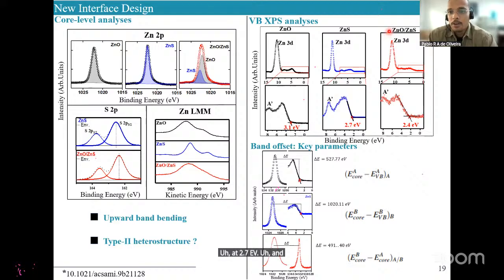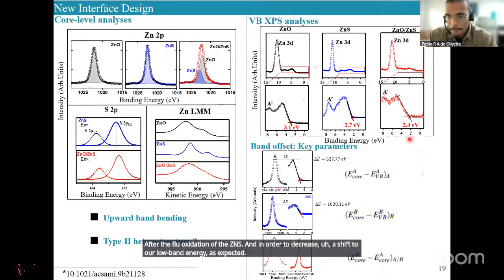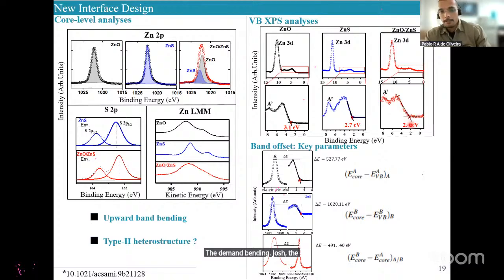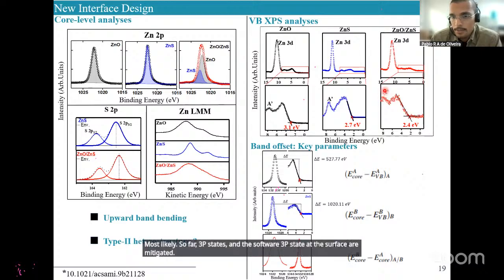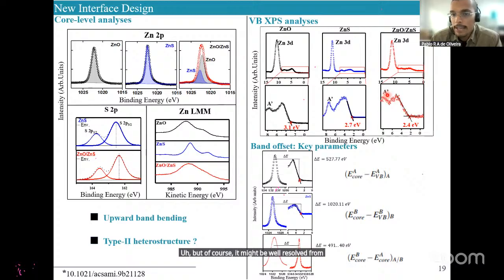Then we compare what happened after the full oxidation of the ZnS, and we noted a decrease, a shift toward low binding energy as expected with the band bending. The shift is toward 2.4 eV. In addition, we can note the suppression of this component A prime here. A prime, in this case of ZnS, is most likely sulfur 3p states, and the sulfur 3p states at the surface are mitigated. Of course, it might be better resolved from UPS measurement instead of XPS, but for the sake of simplicity, it is not shown in this presentation.